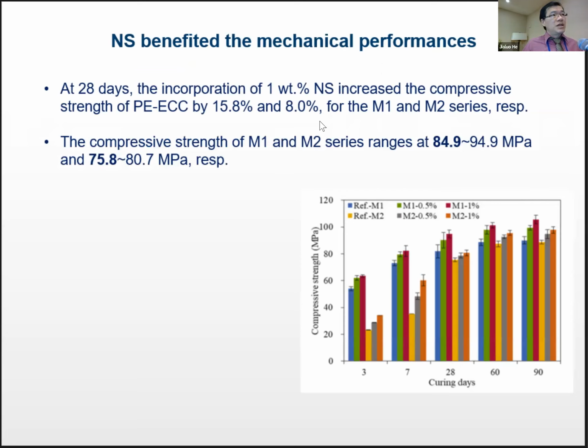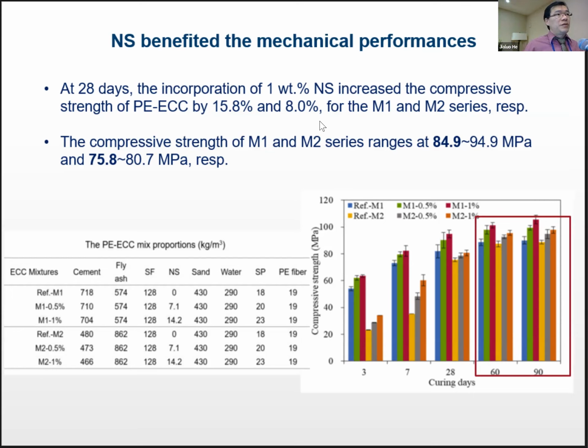Now, in general, the good news is that the nanosilica did benefit the mechanical performance. For instance, at 28 days, the 1% nanosilica improved the compressive strength by about 16% and 8% respectively. So it's not very impressive, honestly, because in most traditional concrete with 1% nanosilica, you'll be seeing something around 20% improvement. But because this is a specialty concrete, we're not surprised. And overall, you can see these 28-day strengths are pretty good, higher than 75 megapascal. And also, by the time you reach 60 days and 90 days, you basically don't see significant difference between the two, M1 and M2. What that means is you can get away with M2 if you're only looking at long-term strength, which has one-third less cement, so it's a lot greener binder. As I will show you later, another unintended benefit was the self-healing was much better in the case of high volume fly ash.